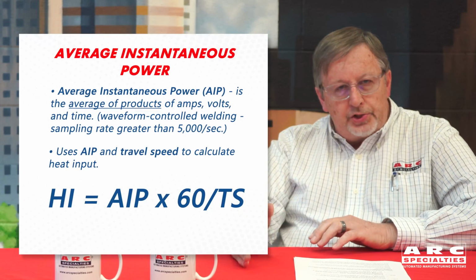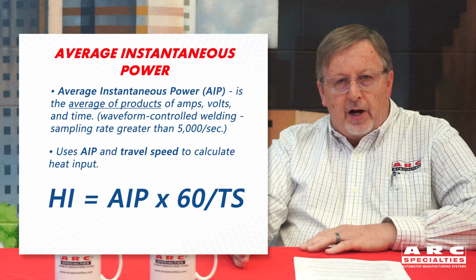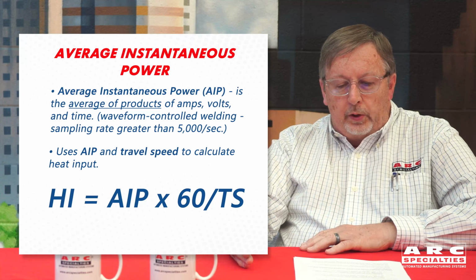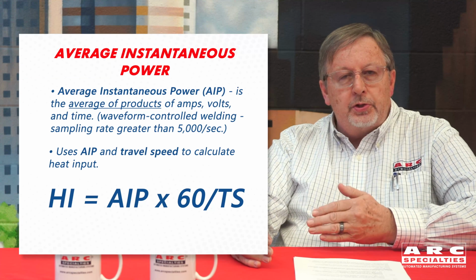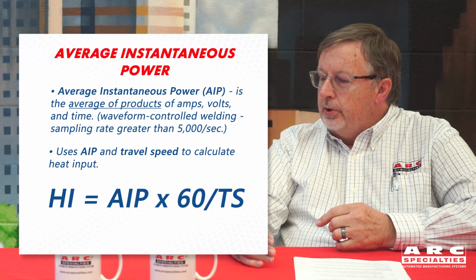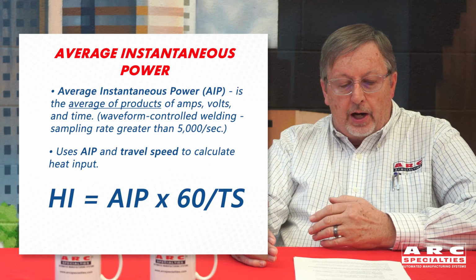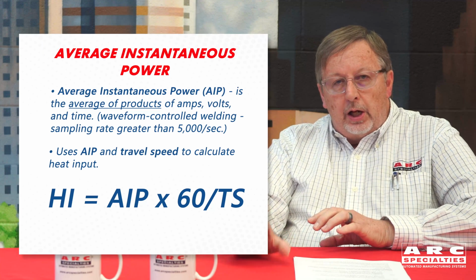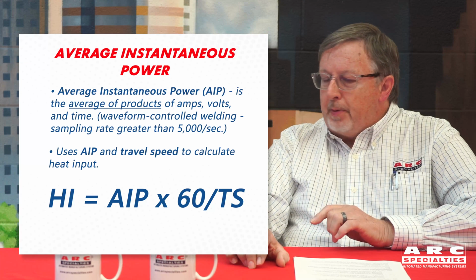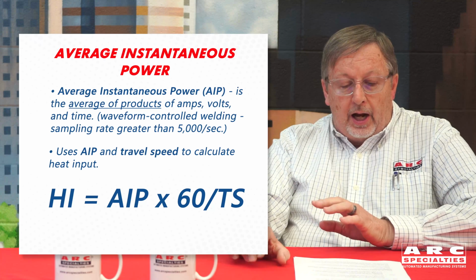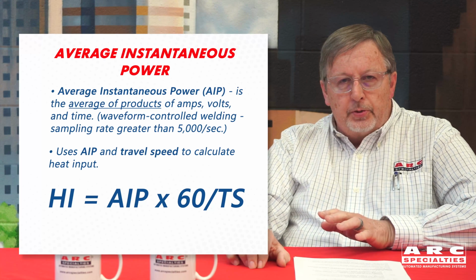Okay. And then we have average instantaneous power. Here, again, we are sampling at least 5,000 times a second, and we are taking the average of those products of amps and volts over some amount of time. So to calculate heat input using average instantaneous power, we divide the average instantaneous power times the number 60 by the travel speed. So again, we end up with joules per inch of weld.